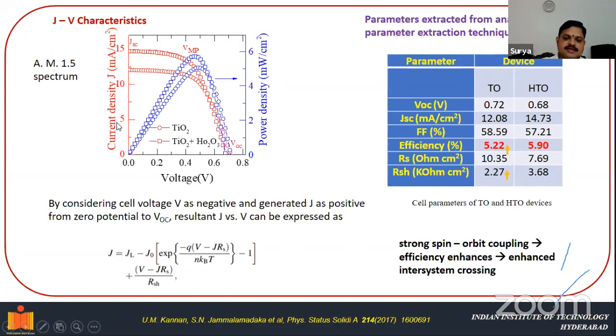So this is the voltage versus current density graph that we have obtained. By considering the cell voltage V as negative and generated J as positive, from zero potential to VOC, the resultant JV can be expressed with this expression. J is equal to this much. Now we fitted these graphs with this equation and obtained the solar cell parameters. What are the parameters that we have obtained after fitting? We have obtained the open circuit voltage, the short circuit current density, fill factor, the efficiency of the device, and the shunt resistance. These are the parameters that we have obtained after fitting these graphs with this equation.